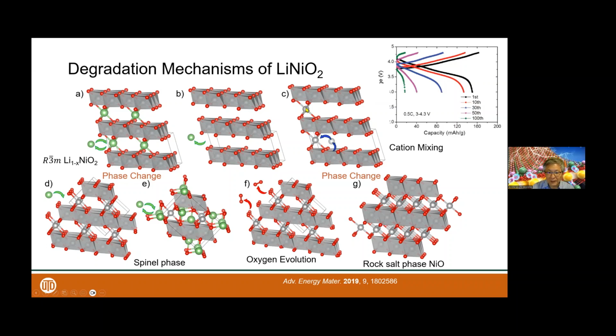At the surface, when we delithiate, the metal atoms tend to come out and form a more rock salt-like structure. To facilitate that, oxygen atoms evolve from the surface and end up forming the rock salt phase. So half of the oxygen atoms, when you remove lithium, nickel-oxygen 1:2 ratio becomes 1:1 ratio. Half of the oxygen atoms from the cathode surface evolve into oxygen gas. This is a serious source of the safety problem of battery material.